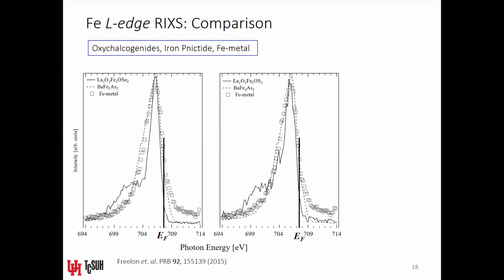So now what I'm showing you is a similar picture as before, but it's blown up. We can compare iron metal RIXS spectra with that of an iron arsenide parent compound and one of our iron oxychalcogenide Mott insulators. And you see that in addition to the occupied density of states being narrow compared to iron metal and the iron pnictide, there's this spectral feature that's close to 8 electron volts away from the Fermi level. So again, this main mass is the dominant portion of the iron 3d band. That type of high energy spectral weight also appears in the sulfur containing Mott insulator.